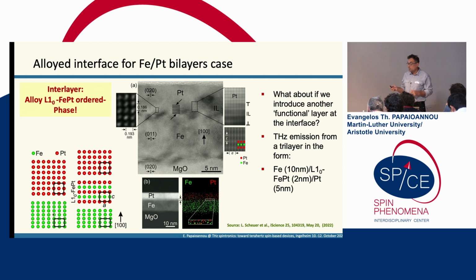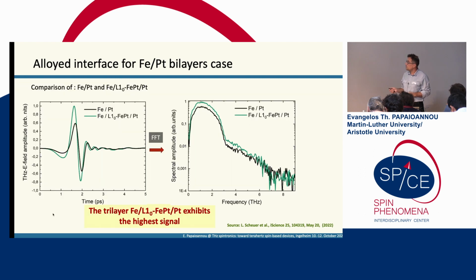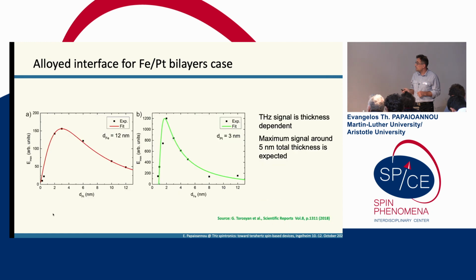Now I will compare the terahertz signals of this special structure. You compare the bilayer and then the trilayer with the alloyed interface in between, and you see that the trilayer with the alloyed interface has a higher terahertz signal. Same waveform, same bandwidth, but the highest signal. So this is one result that we recently published.